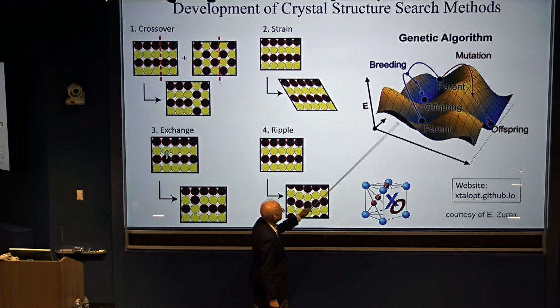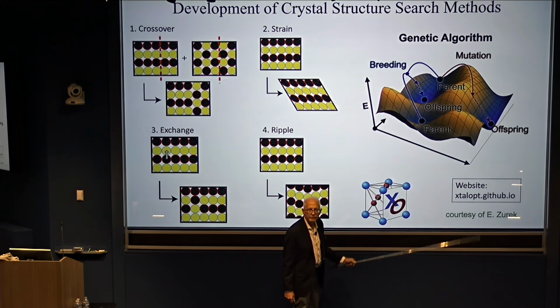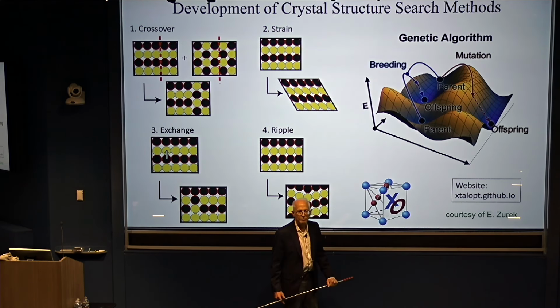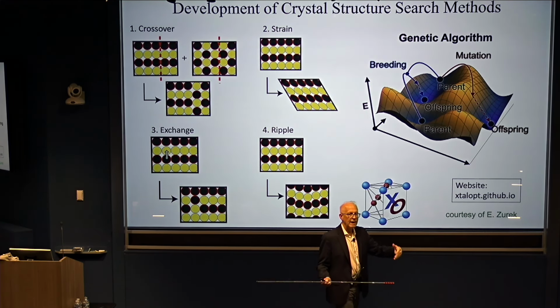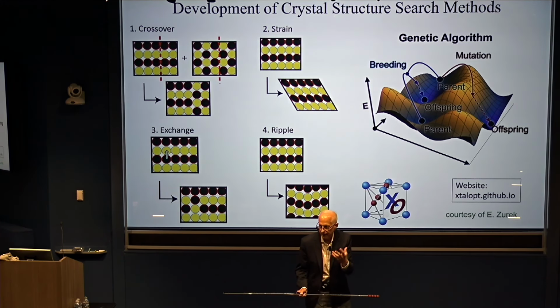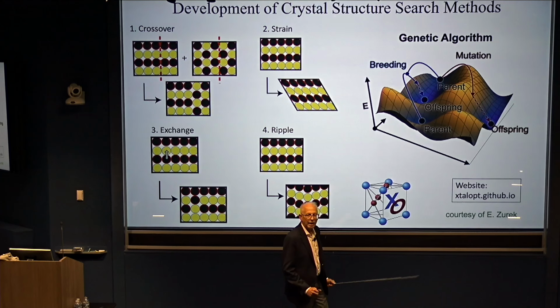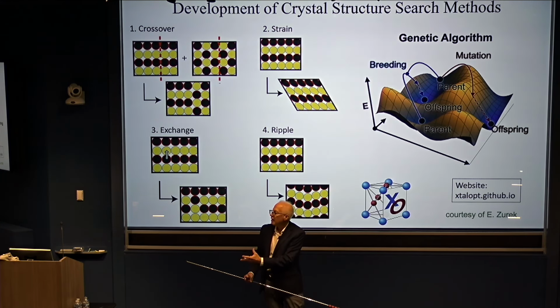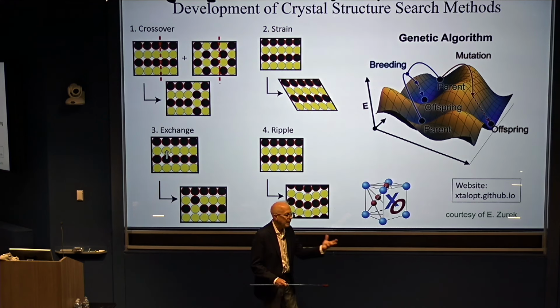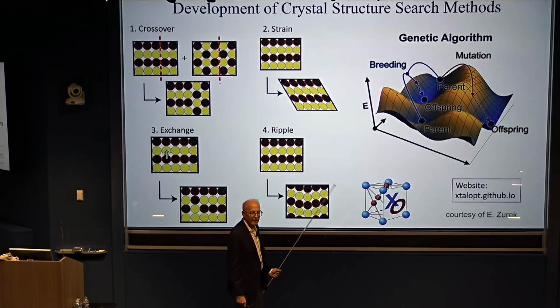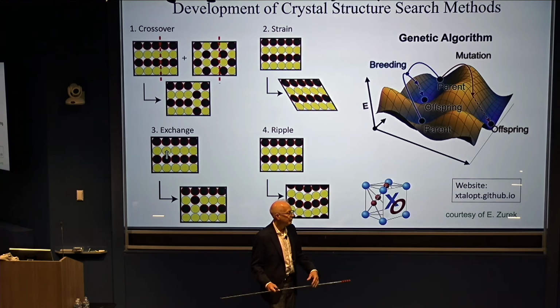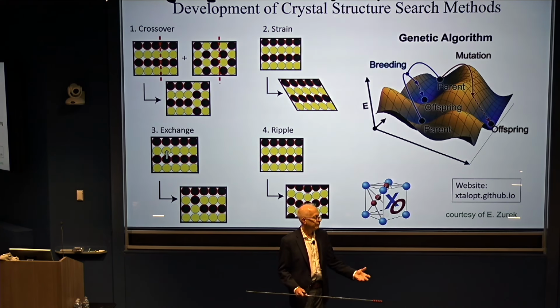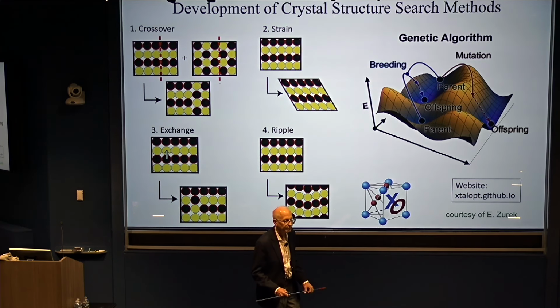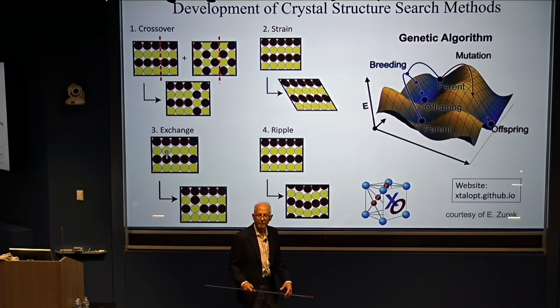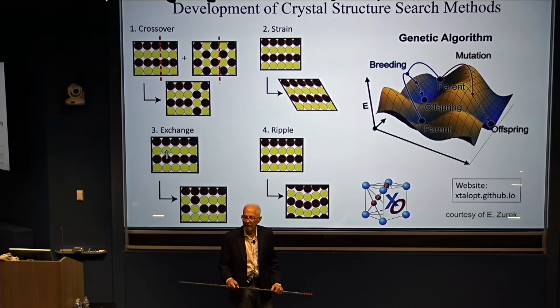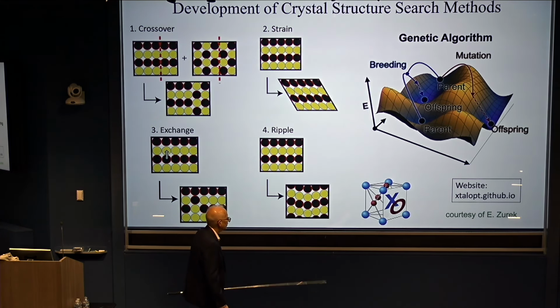You can then feed this into some kind of global picture here on this energy landscape and look for the lowest energy structures. And you have to marry with this, of course, a model for the electronic structure or the total energy of the system. And by this time, density functional theory was working pretty well for some of these elements of interest for that part of the periodic table. So it was really quite successful. These genetic algorithm approaches really led to the discovery of a lot of different materials, not just high-pressure materials and not just the kinds of materials I'm talking about, but really it has been revolutionary. But it was particularly important for guiding us as experimentalists principally in looking for new superconductors.